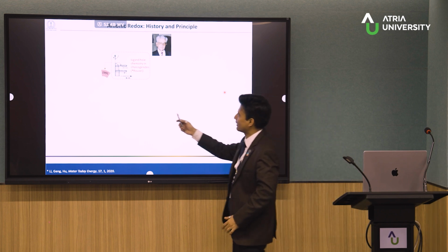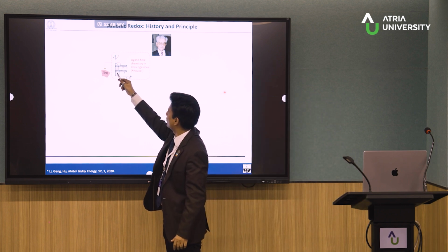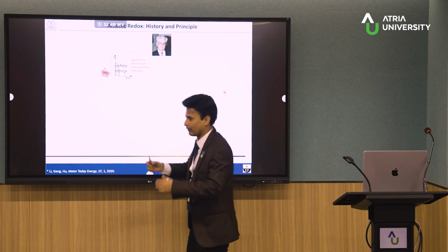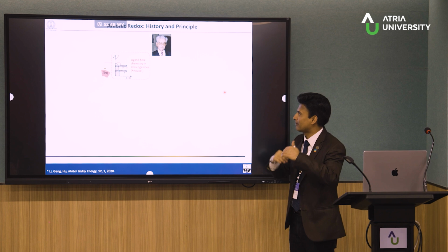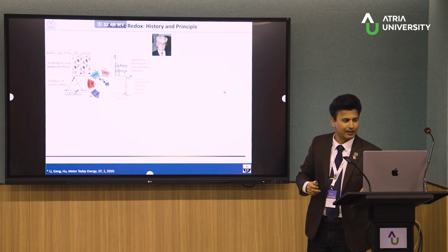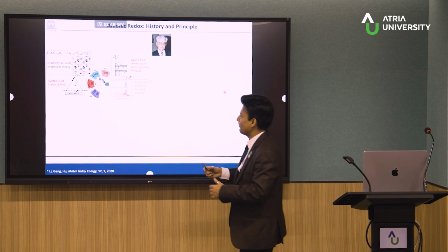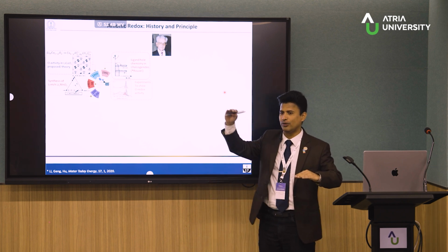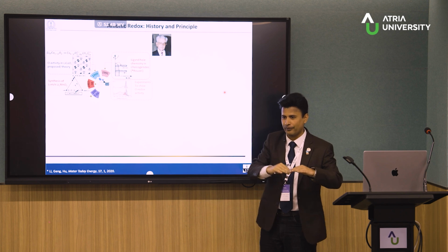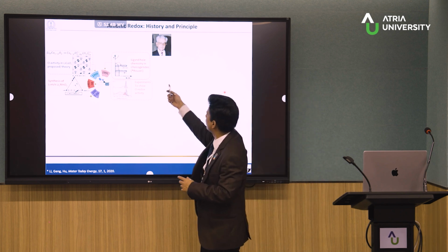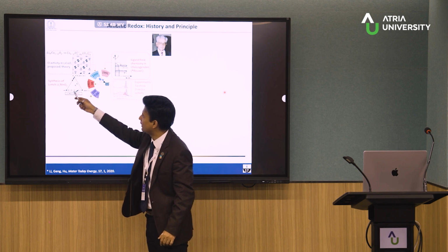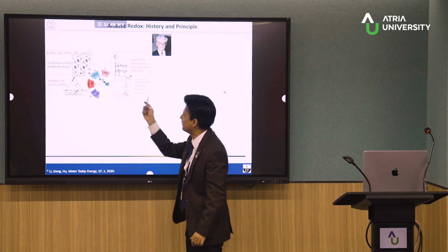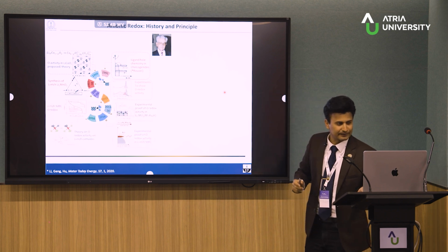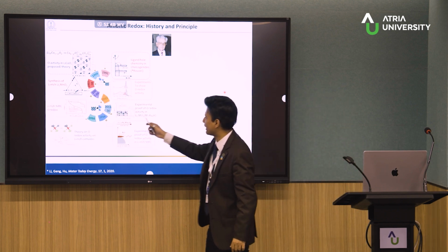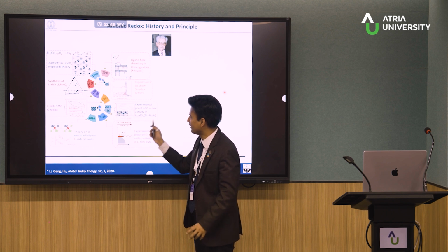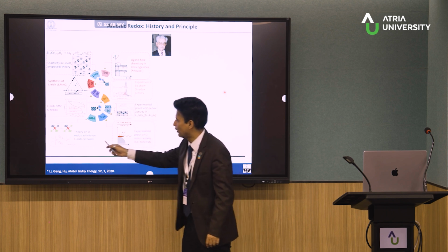So here what we mentioned is that when we have a chalcogenide like a sulfide, it is also possible that before the titanium redox happens, sometimes there is a band overlap, and the sulfur can take part in the redox mechanism. And later, just like from Whittingham to Goodenough, from sulfide to oxide, to increase the voltage, people tried to move from the sulfide to different kinds of lithium-rich oxide and so on, and they found there is a possibility of showing oxygen anionic redox. And then there have been various proofs by wonderful high-resolution TEM, XPS, and so on, and also some theoretical analysis.